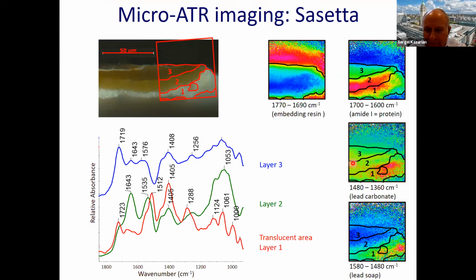This layer, because I want to remove this window. Okay, that's better. Yes, at the bottom. Okay, on my screen, I'm doing some adjustment. So let's start from this one. Distribution of the amide band revealed that protein is actually present, obviously as a binding media. It came from egg and created egg tempera here. But distribution of lead carbonate, which was used as a pigment, was present here. And then what was most exciting, an additional substance was found here, lead carboxylate. And this was really exciting, because I would not show spectra here, but lead carboxylate in such type of samples has not been detected before, because as you can see, it was a very small amount in a very thin layer.